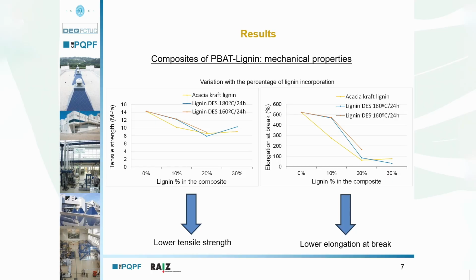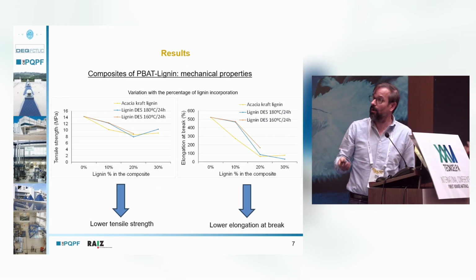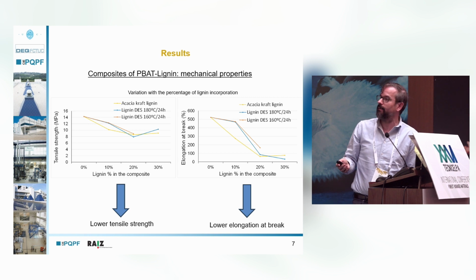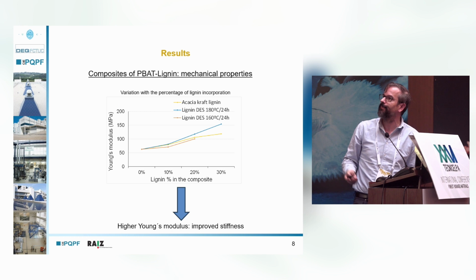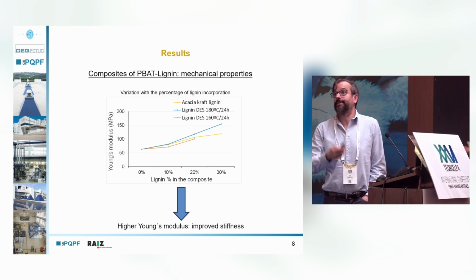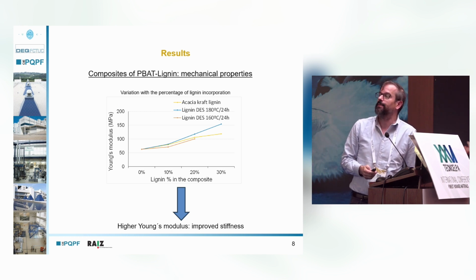Elongation at break of PBAT is very high, this is really real. This polymer is very ductile, has an elongation at break of 600%. So even if it decreases the elongation at break, the final values are not so bad at all. So you have lower tensile strength and lower elongation at break with lignin incorporation in the composites with PBAT. As for the Young's modulus, it increases.